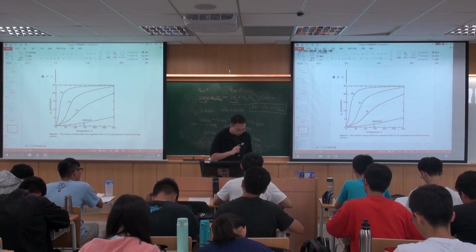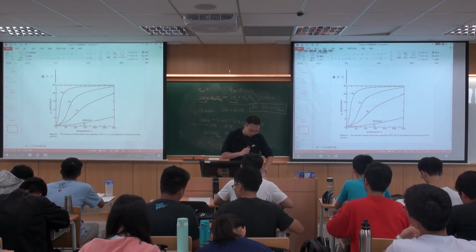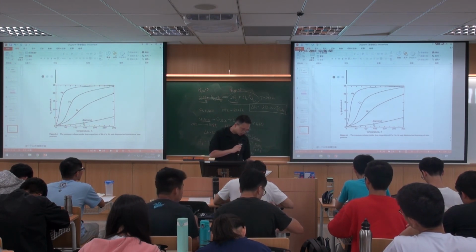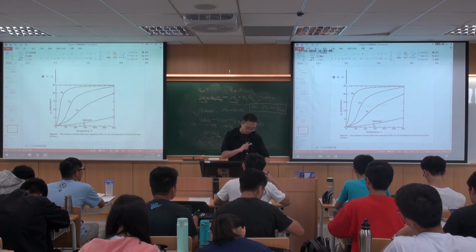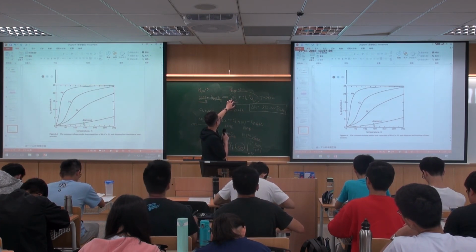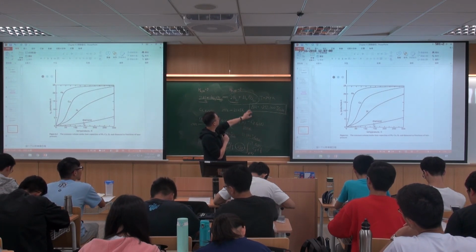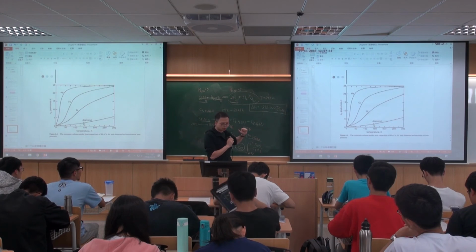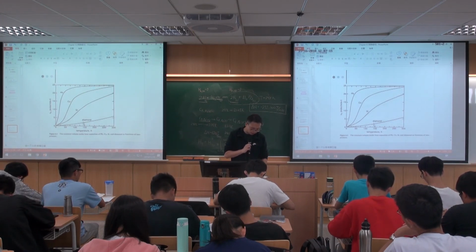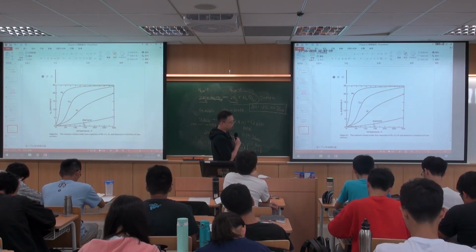Okay, and for this one, it turns out that eventually you will have, I think, 0.05 moles of gas of iron, and the rest of them will be liquid, and this will also be liquid. Okay. So this is quantitative problem 1.